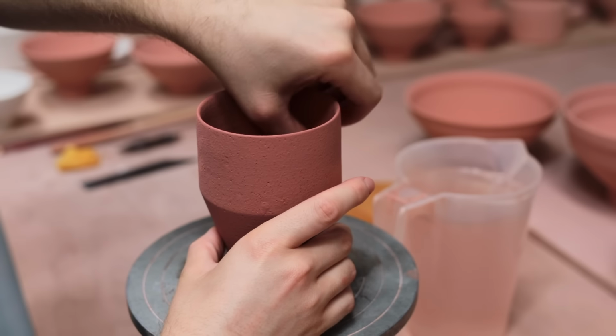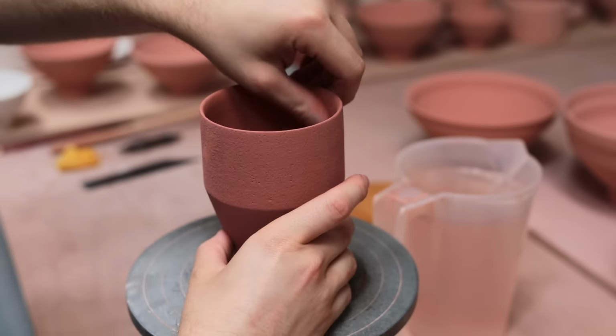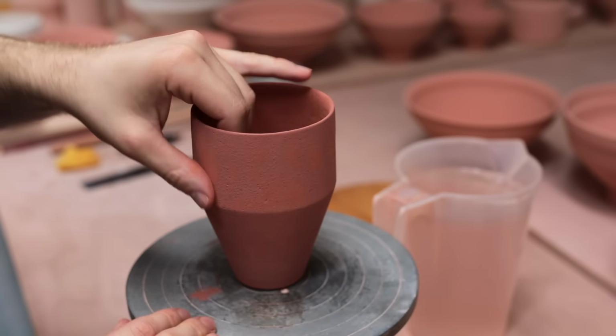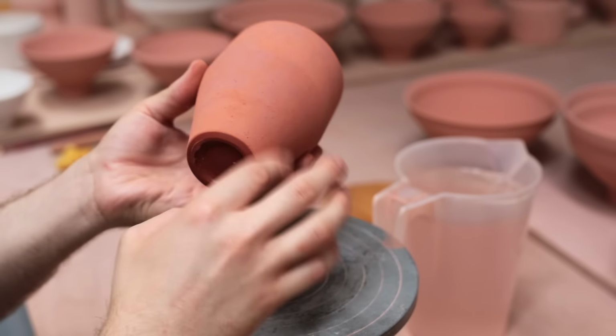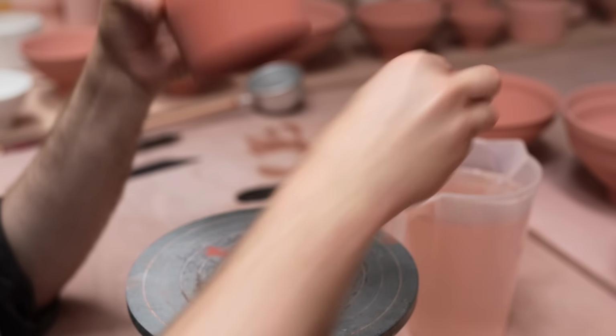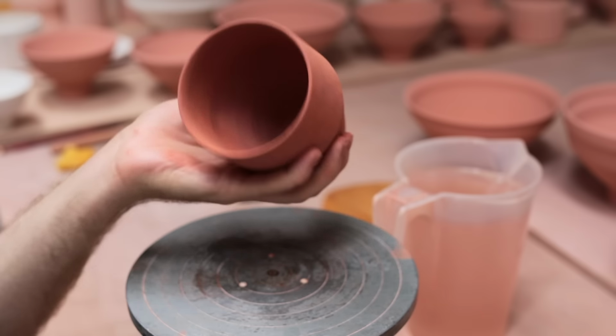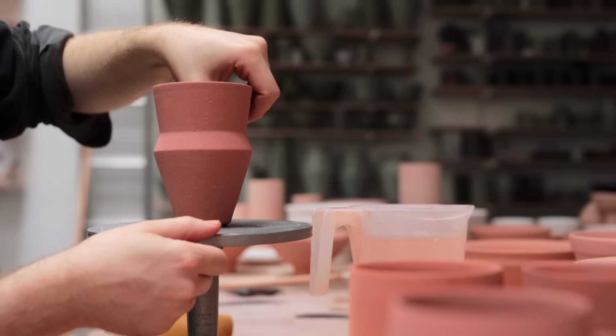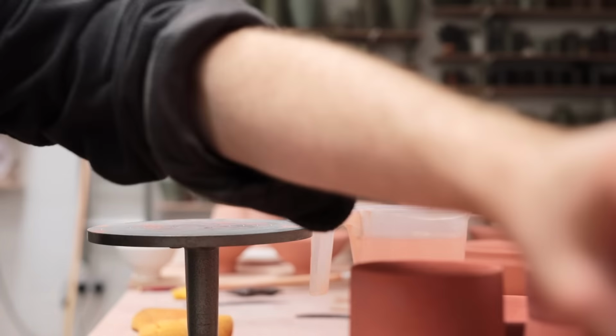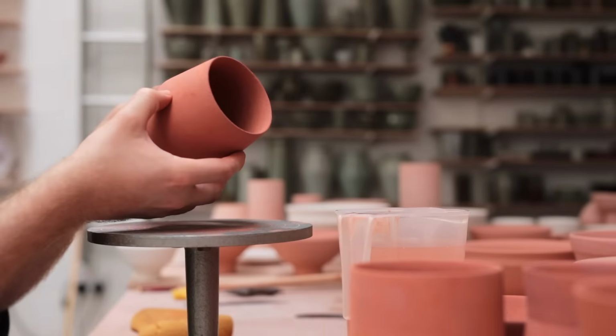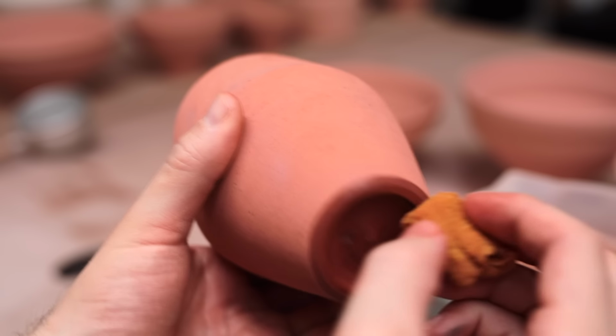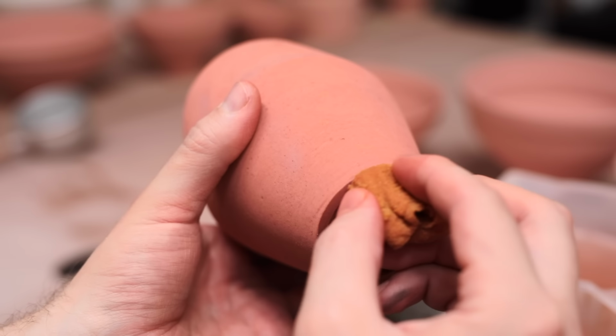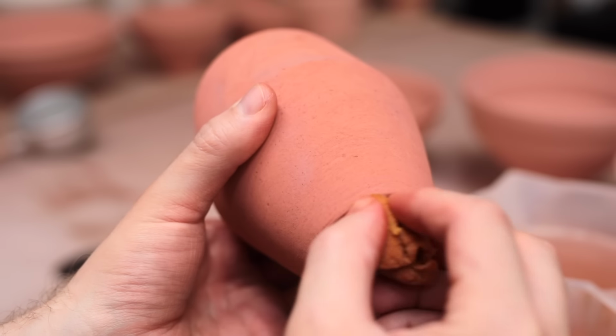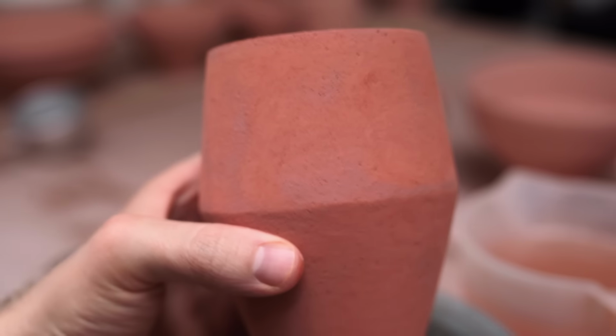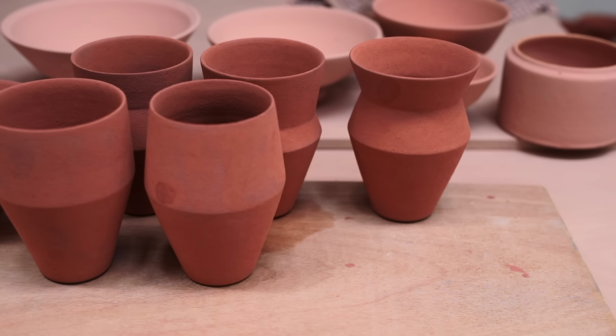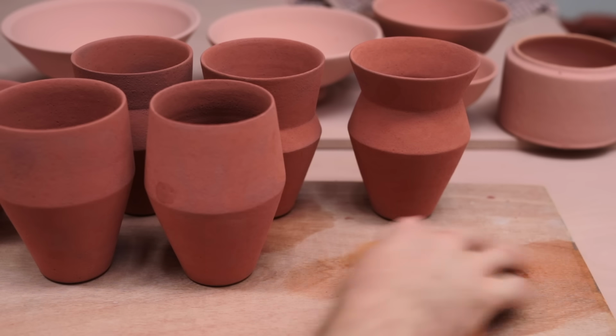This is another process where you have to be careful, as not only is the layer of glaze relatively fragile and can be chipped off if you knock it accidentally, but you can also rub away too much, creating a thin spot that will show in the finished fired piece. It's meticulous work, but it makes a big difference in the finished object, especially the foot. I want the line where clay and glaze meet to be finished to a really neat, even line all the way around. And with all these pieces now tidied up, bottoms cleaned and tong marks removed, the process of packing them into the gas kiln can begin.